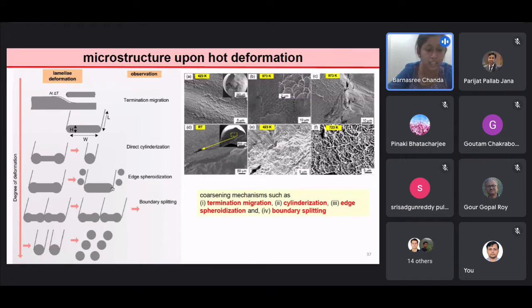deforms into a cylindrical shape. And further, due to maybe Rayleigh instability, it may further deform into spheroidization. And edge spheroidization occurs when the cross-sectional aspect ratio, that is W by H, is large. Boundary splitting occurs due to the presence of a groove between two adjacent curvatures, and the termination curvature moves the lamellae material away from the groove, and leads to the splitting of the groove and creation of the spheroidization.